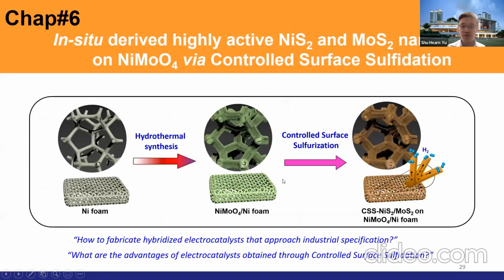All right, so this is my last work. This work is focused on in situ derivation of highly active nickel sulfide and molybdenum disulfide nanostructures on nickel molybdenum microcuboids via surface-controlled sulfurization. So this work is dedicated to high current density. In the first step, I also use nickel foam and do hydrothermal synthesis and grow nickel molybdenum oxide. This is a microcuboid, 1D structure.